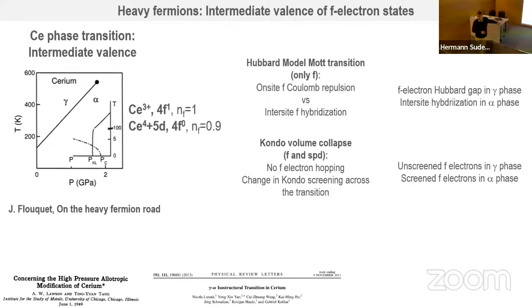Cerium is the only known solid where you do have such a situation. And the reason is that between here and here, you have a volume change by more than 15%, but the structure does not change at all. So the structure of this phase and of this phase is exactly the same. And therefore, you can define this critical point. So what is happening there?